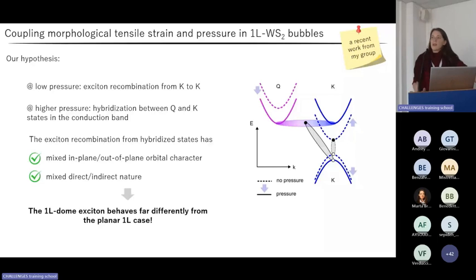This new exciton clearly has a different nature and therefore a different pressure evolution compared with the standard A exciton of planar monolayers, which is localized exclusively in the K point of the first Brillouin zone.